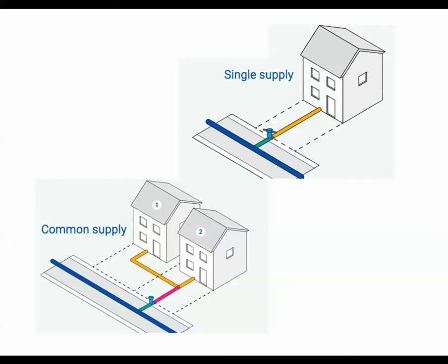So what water companies try to do is make sure that their tap waters, when they pass through the piece of lead pipe, uptake as little lead as possible. They can do things like change the pH, or add little bits of phosphate to the tap water, all trying to minimize that release of lead from the pipe.